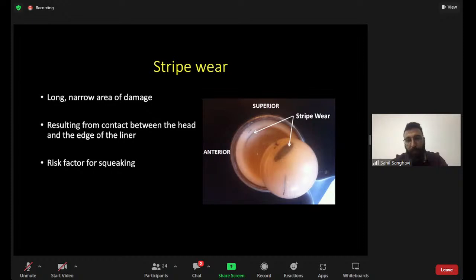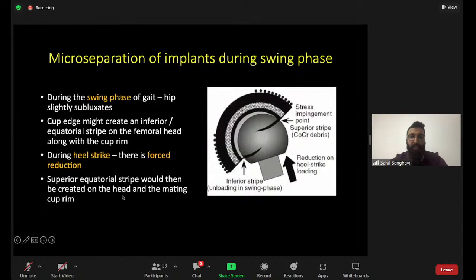Stripe wear is another complication of ceramics, which is basically a long, narrow area of damage resulting from contact between the head and the edge of the liner. This is also a risk factor for squeaking. What essentially happens is that there is micro-separation of the implants during the swing phase. During the swing phase, the hip slightly subluxates, and in the stance phase, the head gets reduced back into the acetabular shell.